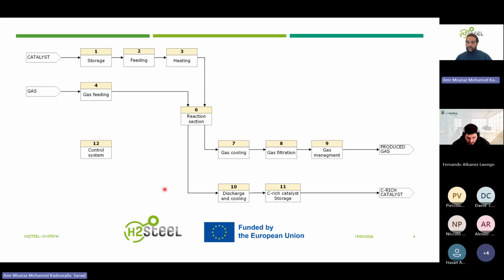By carefully controlling the dosage of the catalyst by the doser and the screw rotations, we can control the level in the bed and maintain it at the desired value for the residence time required. On the other hand, the outlet gases are treated and then go to the gas management for the analysis.